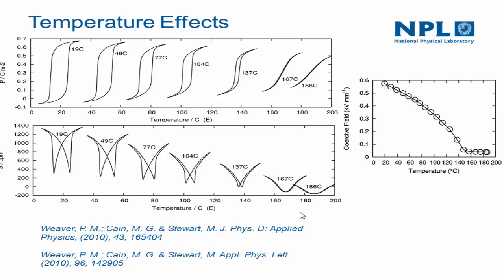And you can see in these strain loops, this is a whole set of bipolar strain loops, and you can see a drift in position which corresponds to the thermal expansion. These are 3-1 strain, and you can see we've got the classic butterfly loop, typical butterfly loop, and then when we get to around the Curie temperature, the hysteresis disappears and we have this electrostrictive behaviour. But if you were to look at the top of the loop, then you wouldn't see any discontinuity going through the Curie temperature. And in fact, even well above the Curie temperature, we're still getting a reasonable level of actuation.